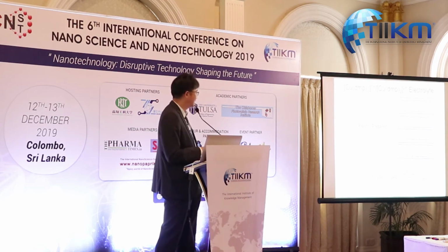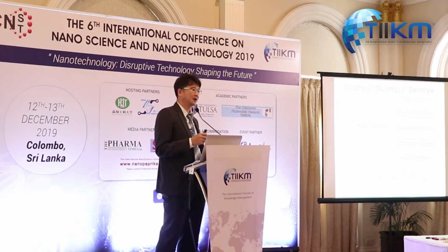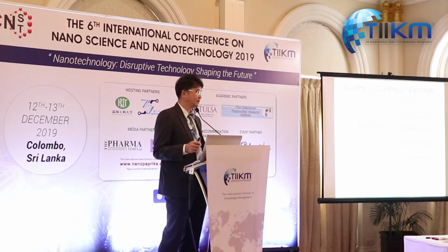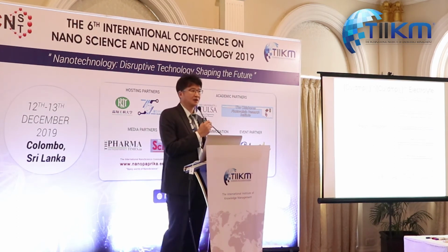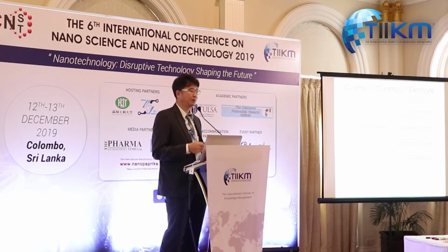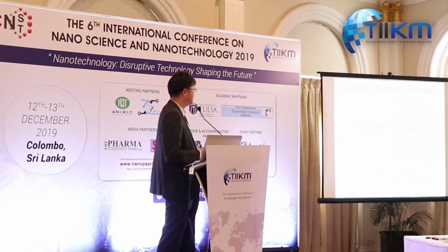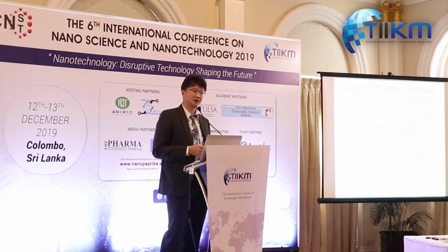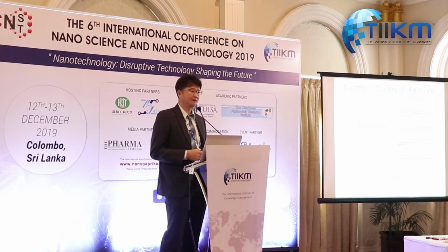It's interesting that the JSC and VOC drop only 5 to 10% after 46 days. And the fill factor drops a lot because of the poisoning of the platinum electrode. So we need to improve the stability of the counter electrode and develop new materials for copper electrolyte for long-term stability.